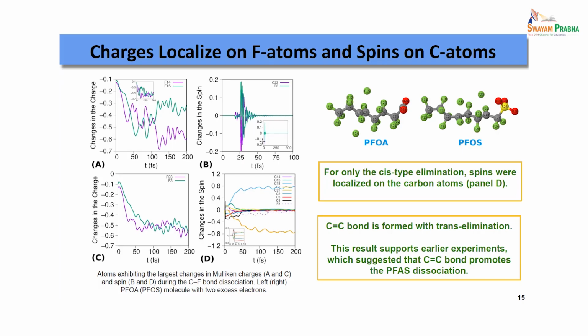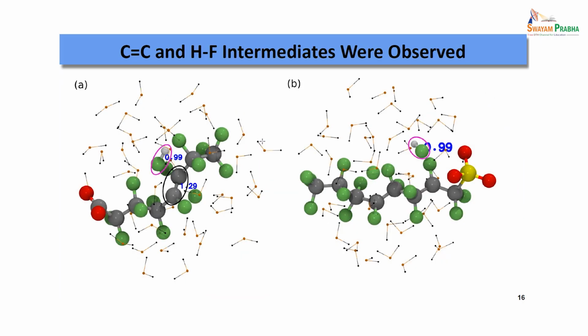Okay, these are just some important points. And what we additionally observed was the formation of a C double bond C after the elimination of these fluorine atoms, and that is helping further to degrade these systems. Essentially, apart from all of these, we also observed the formation of hydrogen fluoride, which is one of the products that was also observed in the experiments. Even the C double bond C was also observed in the experiments, suggesting that these simulations are predicting something good.